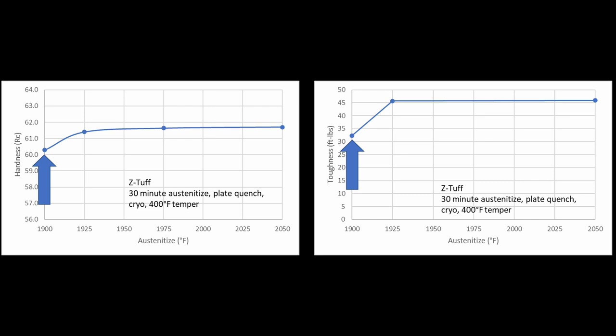With 1900, both the hardness and toughness went down a little bit. So in my book, Knife Engineering, originally, I recommended 1925-400, that being the austenitizing temperature and the tempering temperature, because our properties were so great. I mean, even if they could be improved on slightly, I know that heat treatment will work. And I think that recommended heat treatment will remain the same.